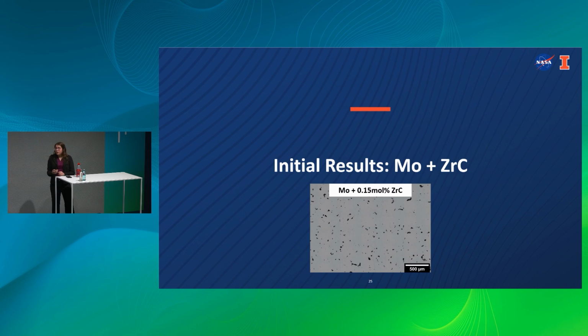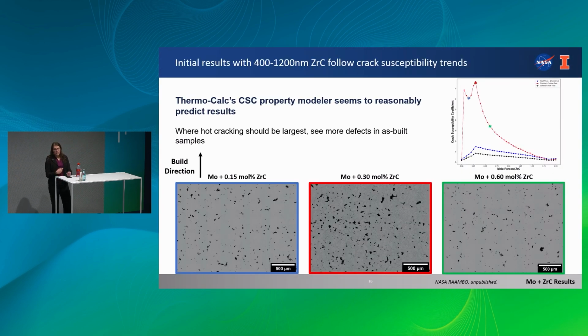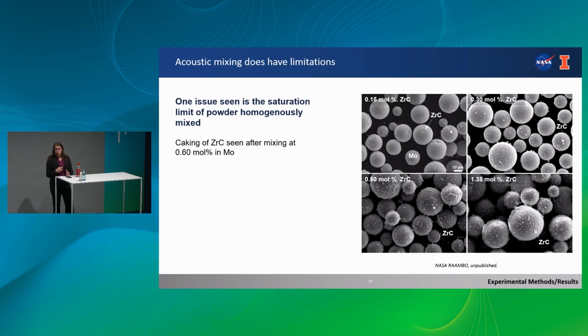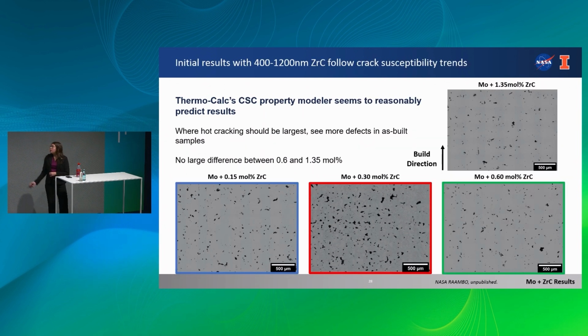So I'm just going to talk a little bit about some of our initial results so far. When we added these different amounts of zirconium carbide to molybdenum, you can see that the highest amount of porosity was where the crack susceptibility should be highest. So this is a bit promising as far as using crack susceptibility to predict some of our results. One thing I wanted to point out is that, like I said, we had this caking, so the 0.6% and the 1.35% have pretty similar amounts of zirconium carbide in them. And so when you add that to the list, they look very similar.